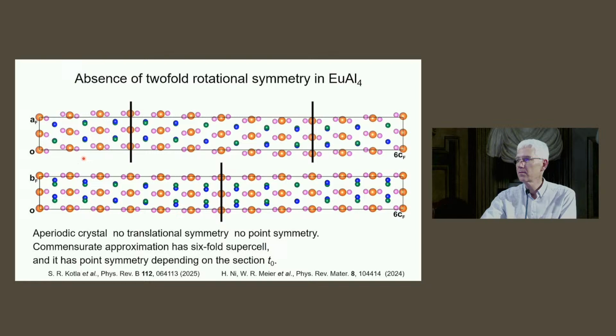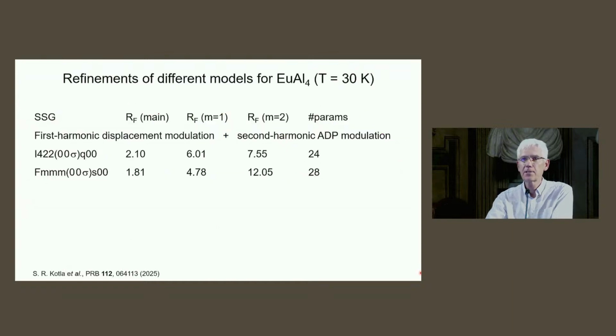So if we want to relate this one with that one, or at the bottom it's even stronger. We see here a green dot with the blue perfectly behind, and here we see the blue on top, but you can also see the green behind. So different displacement in the B direction here and there, and that's as it must be. You can also see this atom is at the lattice point. This atom is clearly shifted along the A axis. So no point symmetry. Nevertheless, convergent beam electron diffraction sees point symmetry if you just look at the experiment.